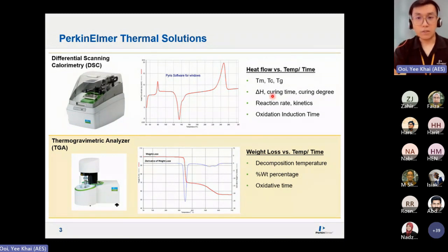Of course, you can do curing as well. For example, thermoset materials like epoxy, or your resin material, acrylic paint, all these things that tend to cure over time. You can use DSC to check as well. What is the curing time? What is the curing degree? Then you can run reaction rate kinetics as well, using the advanced software that is supplied together with the DSC.